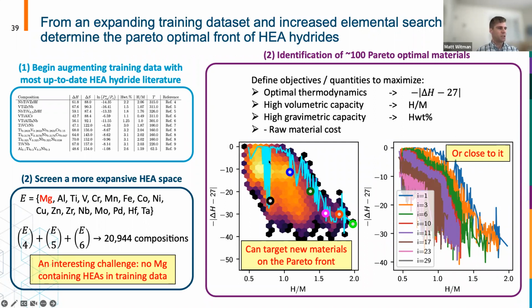So this is a multi-dimensional Pareto front, which I've projected down into 2 dimensions in terms of the delta H and the capacity. But we can rapidly pick out, there's only 100 materials in this blue line. Again, this is the 4D front projected into 2D, but we can rapidly pick out those materials we want to test in lab. And that's what we're going about doing right now.